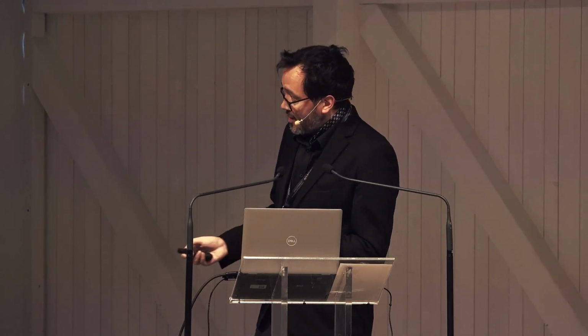This model provides very useful information for industry. For instance, how the particles disperse in the slurry as a function of the particle size distribution of the anode material, as a function of the formulation, as a function of the solid content, which are all properties that are controlled at experimental level, right? And therefore, this gives information about the rheology of the slurry. And this is something that industry needs to optimize properly in order to have beautiful coatings, to produce beautiful electrodes without cracks, for instance, right? High quality electrodes.